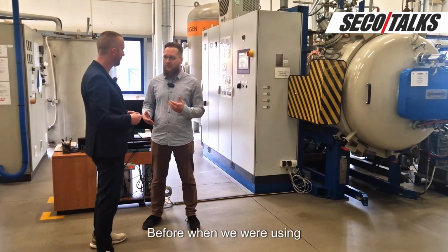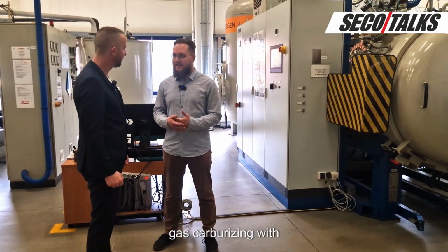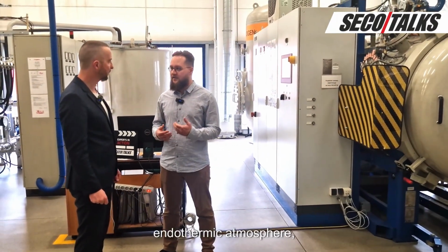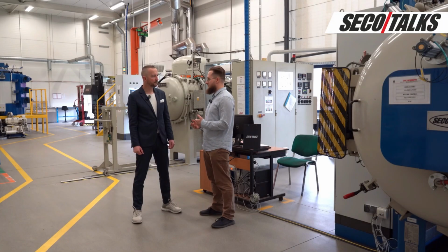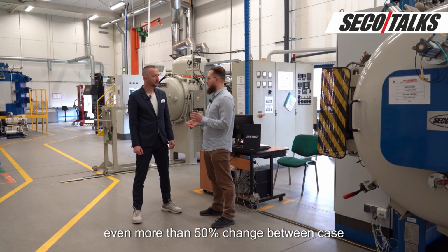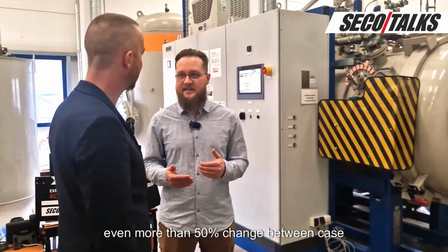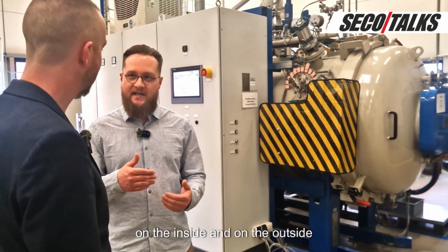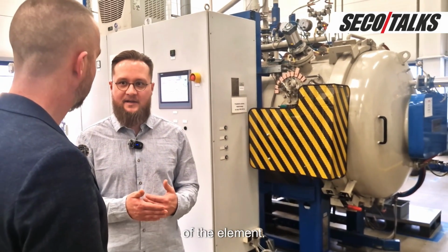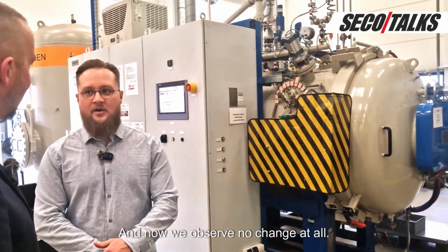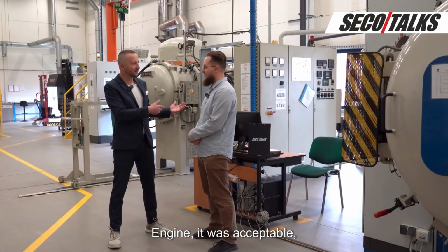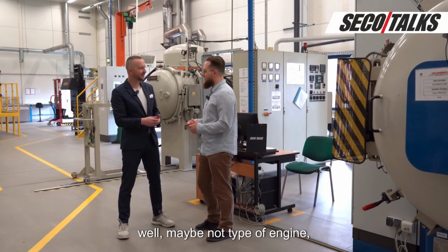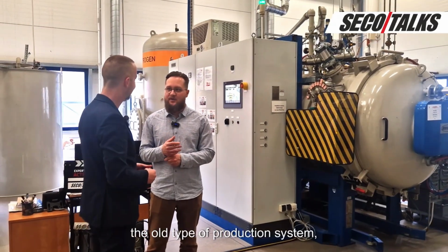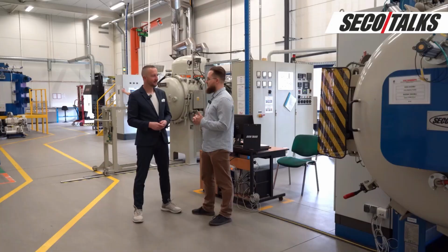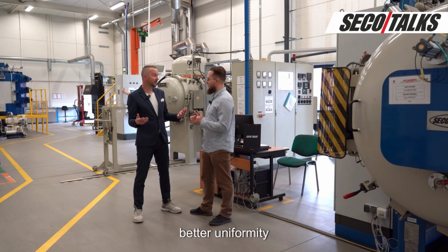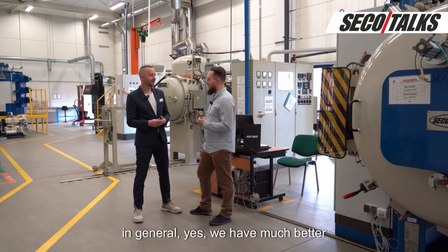Before, when we were using gas carburizing with endothermic atmosphere, we could have even more than 50% change between the effective case depth on the inside and on the outside of the element. And now we observe no change at all. The old type of engine, it was acceptable. Yes? Well, maybe not type of engine, the old type of production system, much better. Better uniformity, in general. Yes, we have a much better uniformity.